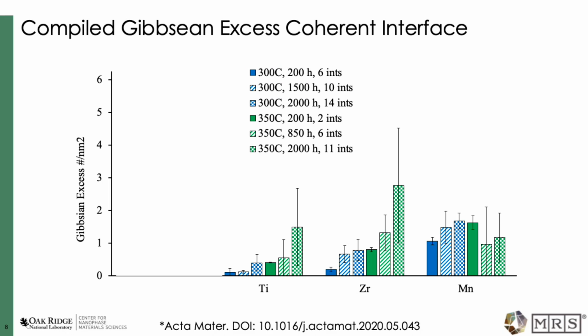The solute segregation behaviors at the theta prime coherent interfaces were compared using Gibbsian excess calculations. Several samples exposed to different temperatures and periods of time were used. The number of interfaces used in each Gibbsian excess calculation is shown in the legend. Titanium and zirconium continue to segregate to the theta prime coherent interfaces for all temperatures and times studied, while manganese does not continue to segregate to the interfaces for times above 1,000 hours at 350 degrees C.